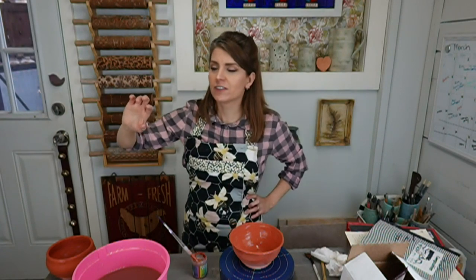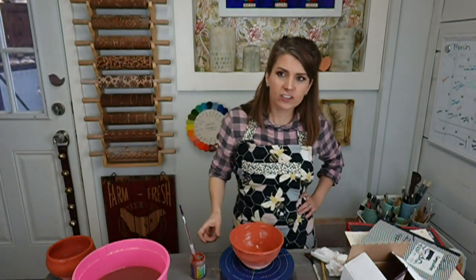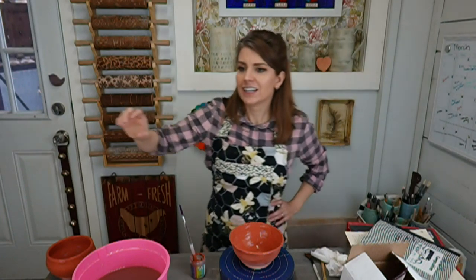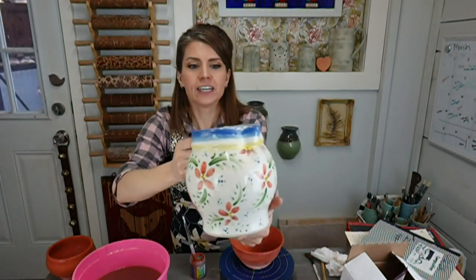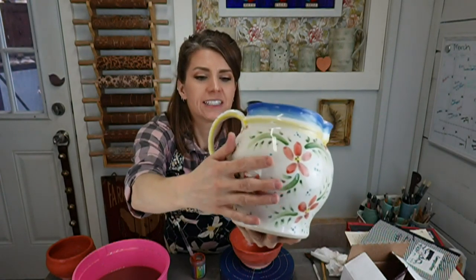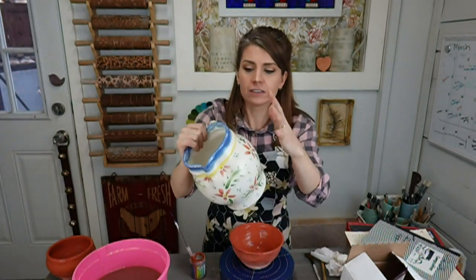You'll see there's a whole series of the Majolica pieces, and there's a picture, there's a plate. I did a class on the Majolica with underglaze, so this is an updated version, and what I want to show you is if you look here, you will see the reds, and even the blues aren't really moving a lot there, but I went a little heavy on the inside of the rim with the blue, and do you see how we got fluxing and melting there? So with the blues, you tend to get fluxing. This is B-Mix with white glaze. It's actually Clayscape's cream. I dipped the entire thing in cream, and then I painted on the surface with underglaze.